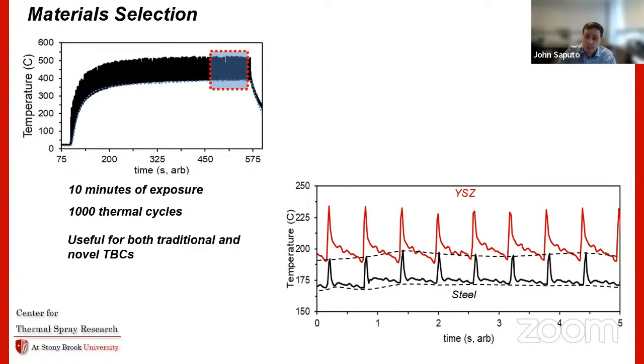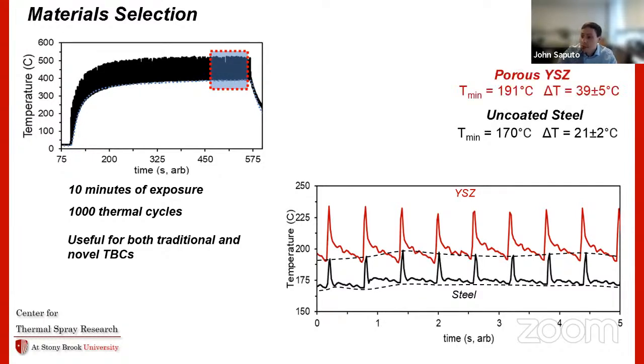The first is that temperature jump that I was talking about before. So for steel, it's about 21 degrees, and that baseline temperature is about 170 C. For zirconia, that temperature swing is about 40 degrees. And the baseline temperature jumps up, which would be bad because it would degrade the thermodynamic efficiency of an engine by heating the intake gases.